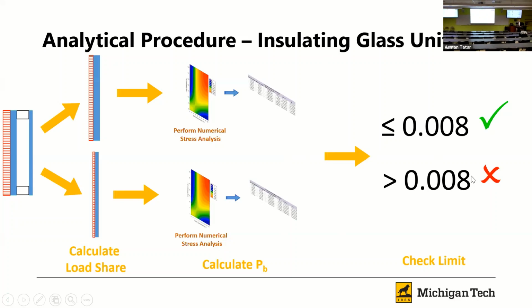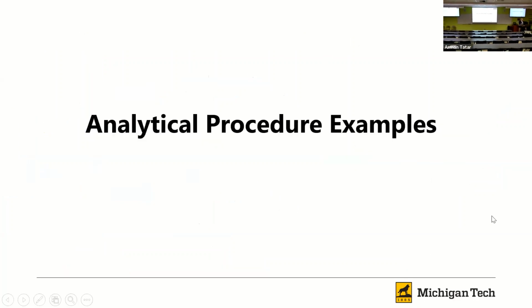So that's not too bad. We could see that if we branch out and one of these was laminated, then you would see that break out, and we would potentially have to do 3 stress analyses if we're using the effective thickness model. The other alternative is to model the laminated glass directly as a layered system, and then you don't have to worry about doing the effective thickness model.